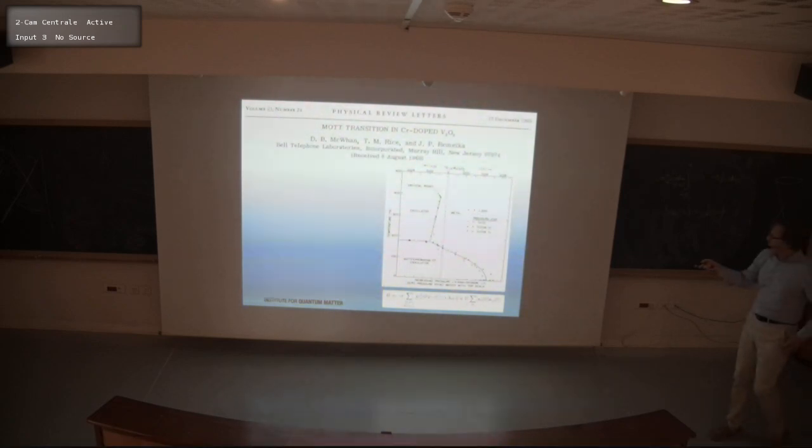Now, you can see what it is that allows the experimenters to move across this phase boundary. Well, it turns out to be chemical doping. So this is not temperature, and it's not actually pressure, because the pure V2O3 compound is already in the metallic state. So I'm not able to have less than zero pressure, and so what is done then is to introduce chromium to effectively increase the on-site repulsion, or introduce titanium to decrease the on-site repulsion. Then I can move across this boundary.